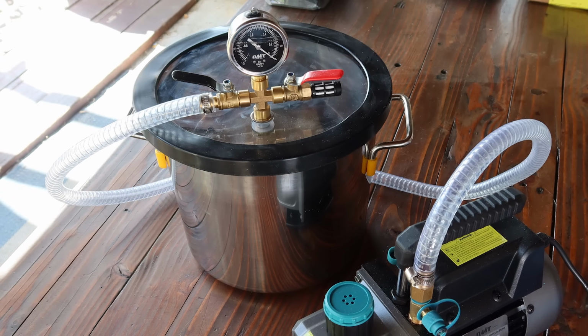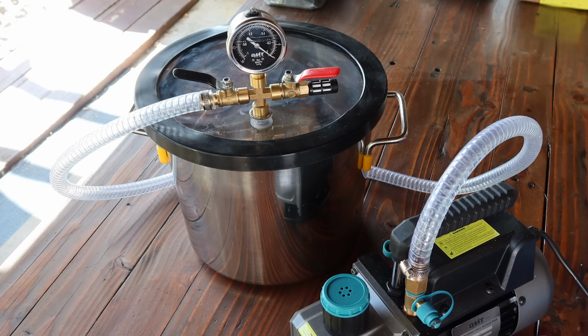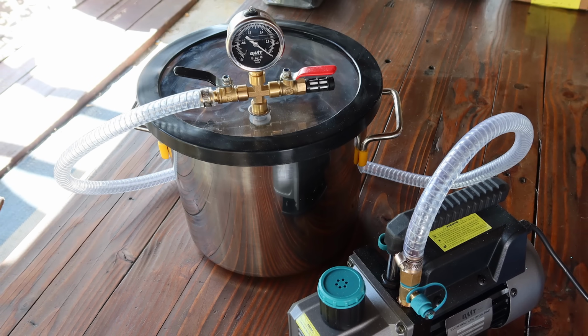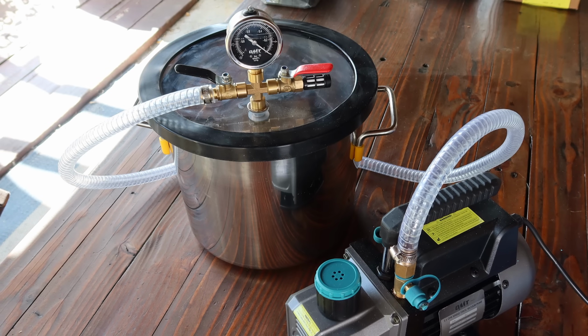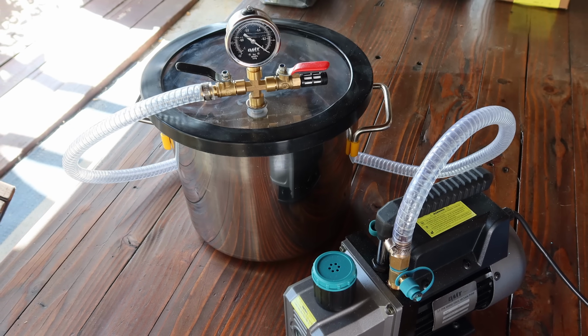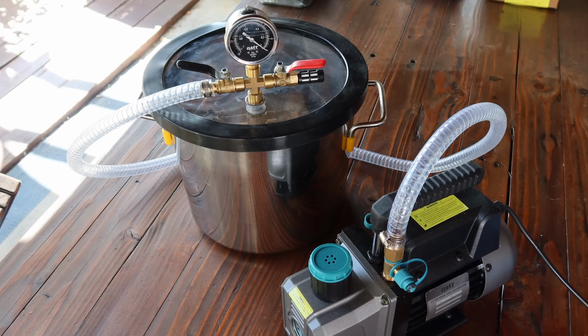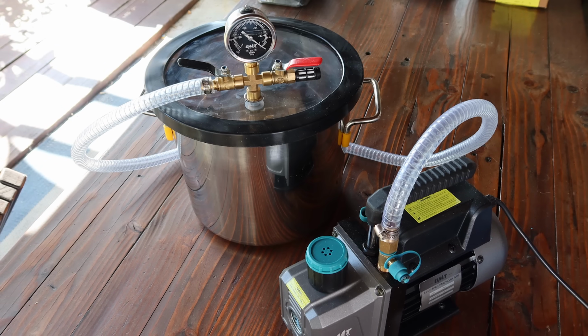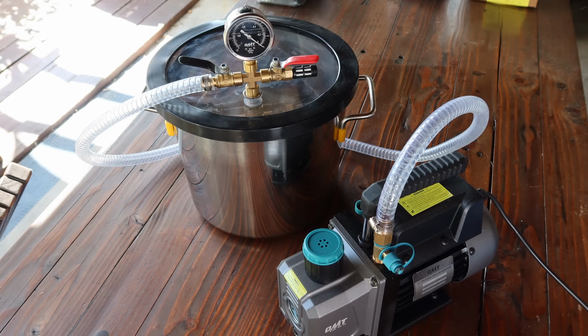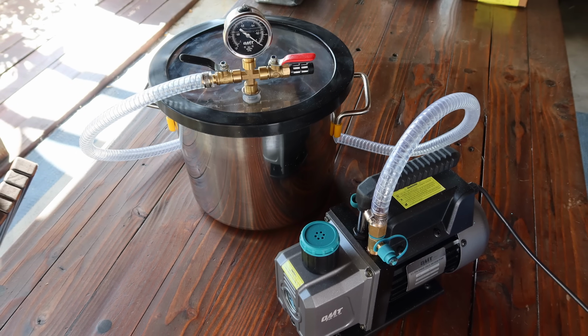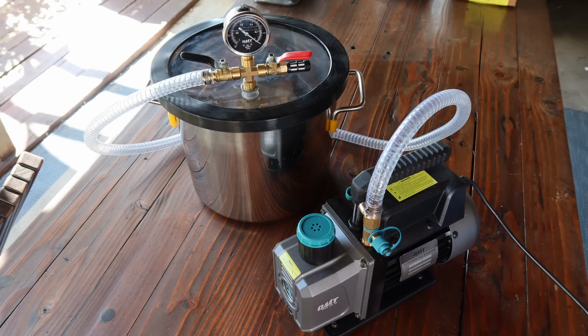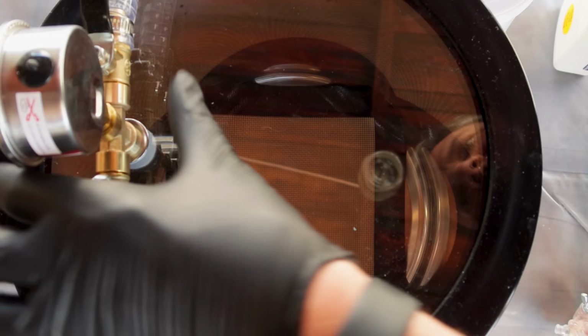Whenever you mix together multi-part liquids like this, you're going to be introducing a lot of air bubbles into the mixture. This becomes a pretty big issue if you're trying to cast clear or translucent parts. Those micro air bubbles will get suspended in your resin and it'll just come out looking really bad. To get around this, you can run your resin through a vacuum chamber. This will degas the mix and make it so you can get crystal clear parts.